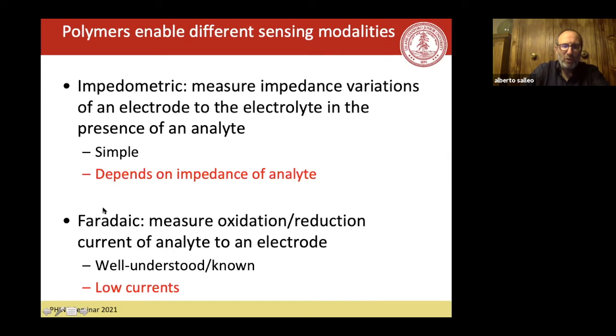Another way to sense is Faradaic. So essentially you have your target molecule and then you have it land on an electrode and you oxidize it or reduce it, so that will produce a current. So you measure the oxidation or reduction current of the analyte to an electrode. This is a very well understood and known way to do electrochemical sensing. People know how to do it selectively by using, again, these ion selective membranes, for example, or using enzymes.